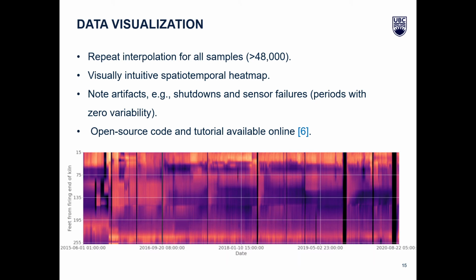If we take the horizontal color bar from the previous slide, rotate it 90 degrees, repeat this for every sample, and append them together, we get the spatiotemporal heat map shown here. The measurement position is shown on the y-axis and the date is shown on the x-axis. This approach allows us to intuitively visualize over 5 years of kiln shell temperature data. From the heat map, we can see events such as shutdowns, which are shown by the black vertical bands. We can also see extended periods with zero variability, where the camera is not operating correctly.